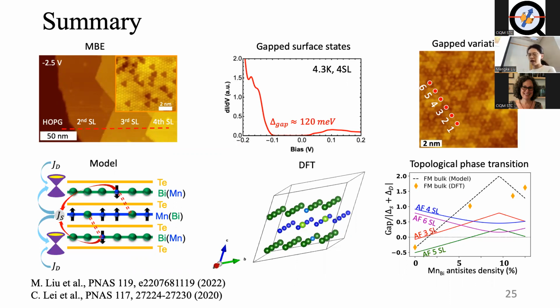Yeah. So the question is, how do we do the growth? Whether we did a bismuth telluride, manganese telluride anneal, or we co-deposit, or whether we can control which termination of the layer we have. The answer is there are many ways. In MBE growth, there are generally two ways to do the growth. Either you alternate the growth of bismuth telluride and manganese telluride, and you anneal and make the manganese telluride sink into the middle of the bismuth telluride, or you co-deposit them together. You open up the shutter for bismuth, manganese, and tellurium, and then they form a well-ordered lattice. In this specific case, we did a co-deposition. So three of the Knudsen cells, we open them together at the same time, and they deposit on the surface.